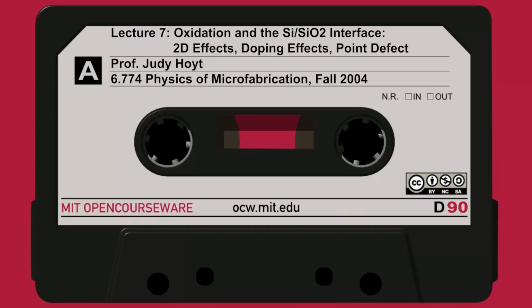So this was the SWAMI structure. They're very similar to recess LOCOS. You create the recess, but they create an oxide mask here, and they also put a pad oxide and a nitride mask along the edge of the recess, and even at the very bottom, at the foot. So trying to minimize the oxidation in the active device region by masking the etched sidewall.